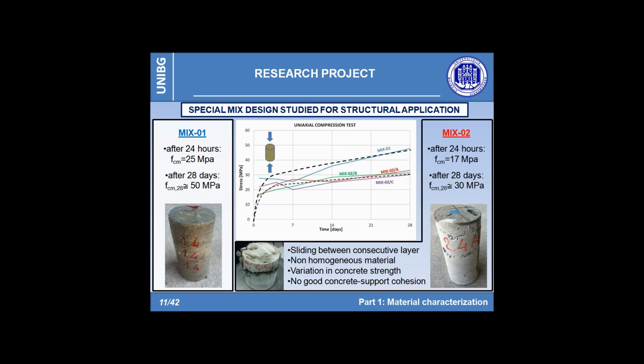thus ensuring the possibility of erecting the structure with an extremely fast construction process. Concerning Mix 2, different problems regarding sliding between two consecutive shotcrete layers and detaching from the support have suggested to modify during the casting phase the mix by adding different types of plastic fibers. Nevertheless, the result of the test haven't proven to be up to expectations, thus suggesting to adopt the Mix 1 to proceed with the experimental campaign.